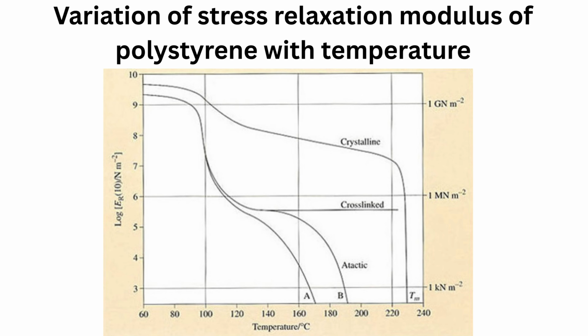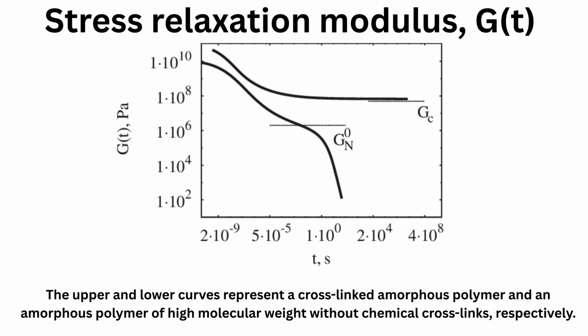Although atactic PS is inherently non-crystallizable, the isotactic form can crystallize, and its melting point, Tm, is about 230 degrees Celsius. Molecular mass also affects the stress relaxation spectrum, particularly at intermediate and higher temperatures greater than 100 degrees Celsius. For high molecular masses, only the rubbery plateau and viscous flow regions differ markedly. The glassy and transition regions are unaffected. Increasing molecular mass clearly improves some mechanical properties, but nowhere near as effectively as crystallization.